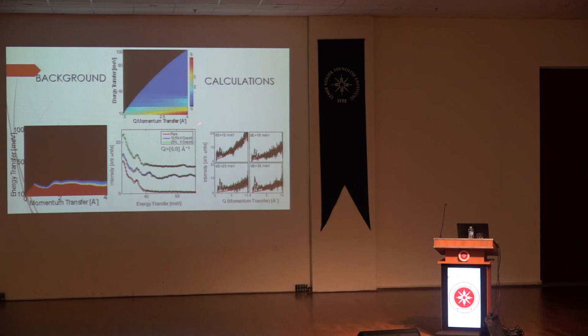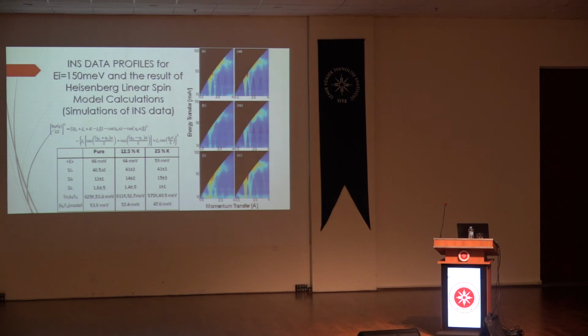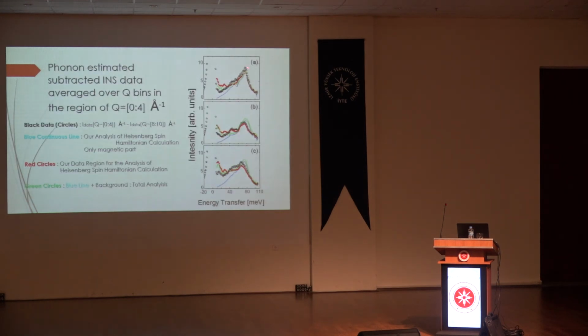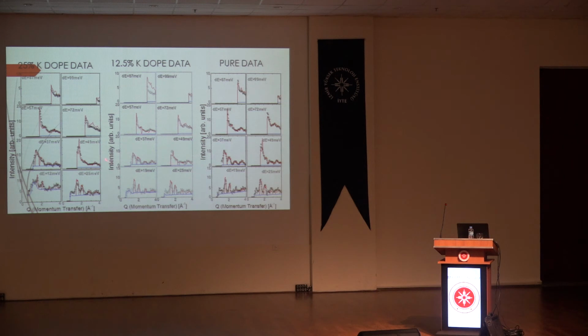So, back to the background calculation, as you see, we have that background at the end. We fit the high part with the quadratic information between 6 to 8 Angstrom, and I even fit more of it. Also quadratically, I carried the fit values back to the region of interest there. This is the whole scattering for manganese oxide. We also calculate that with the same code that we wrote. When we add all together, this happens, and that is basically there beneath. That is also a good way of comparing, but I'm not going to go into details. This is the idea of taking the two-dimensional data with respect to my calculation. If you ask questions, I'm going to tell the details. That is the whole picture of how they fit each other.